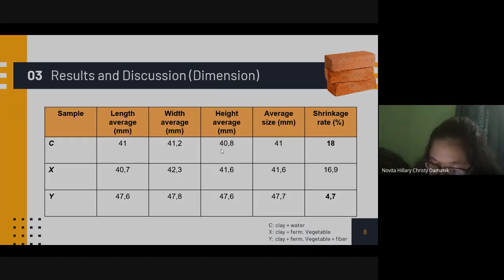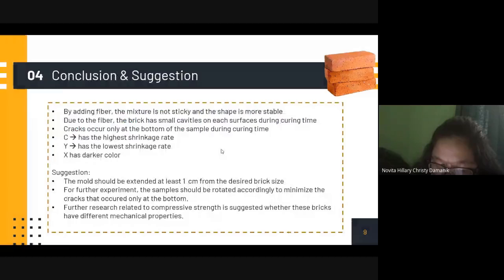So, to conclude, the effects on visible properties such as dimension, texture, and color are: first, by adding fiber, the mixture is not sticky and the shape is more stable. Second, due to the fiber, the brick has small cavities on each surface during curing time. Cracks occur only at the bottom of the sample during curing time. And C has the highest shrinkage rate, Y has the lowest shrinkage rate, and X has a darker color.